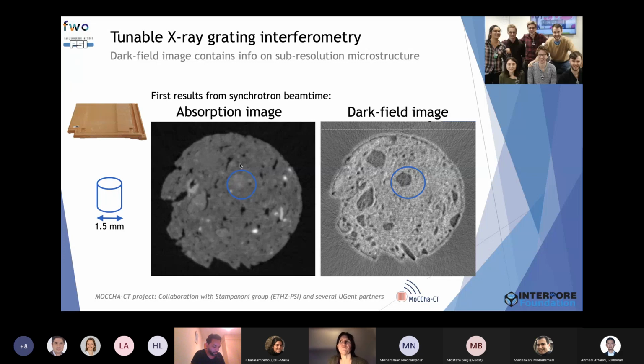This can be important if you want to know if you have a rock which consists of dolomite and calcite, and you have difference in gray values. You want to be sure that the difference is due to the fact that you're dealing with dolomite versus calcite, and not because your calcite contains microporous zones which are below resolution, and because of a partial volume effect you cannot distinguish them.